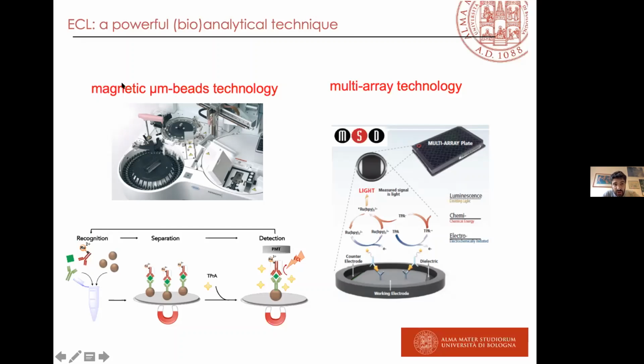The combination of this kind of technology with microbeads is very important and very useful in the field, because you can have magnetic separation of the beads. You can use a magnetic field to attract magnetic beads onto the electrode. On the magnetic beads you have the sandwich assay, and afterwards you can generate the light by simply applying the potential. The other application is from Meso Scale, and in this case they use a different approach. It's a multi-well plate, but they still have the sandwich antibody on the electrode.